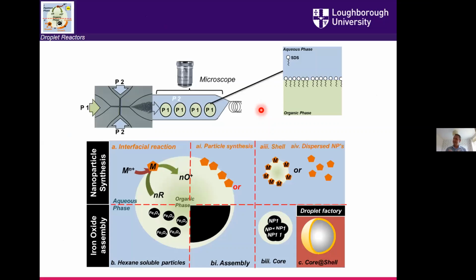And the cartoon schematic of what I had in my mind to do this is here, in that I wanted to create a droplet. Those droplets would then act as an interface to be able to not only encapsulate iron oxide particles within them, but to be able to be a loci for a specific interfacial chemical reaction, so that I could control the reaction that took place on the outside, and it would end up encapsulating something that we put on the inside of the droplet. And so I was trying to combine those two parts of my life and career, where we were making these magnetic particles within the droplet, but then I wanted to apply some of that interfacial particle chemistry that we'd come across earlier on.